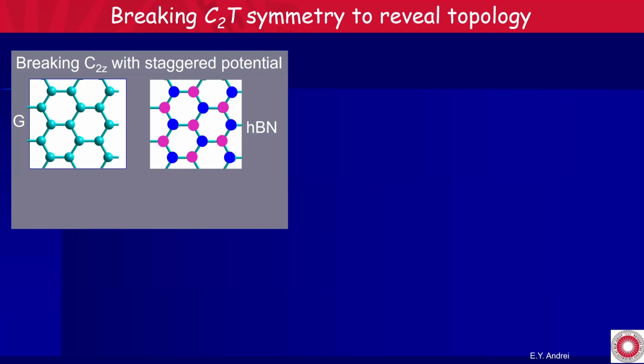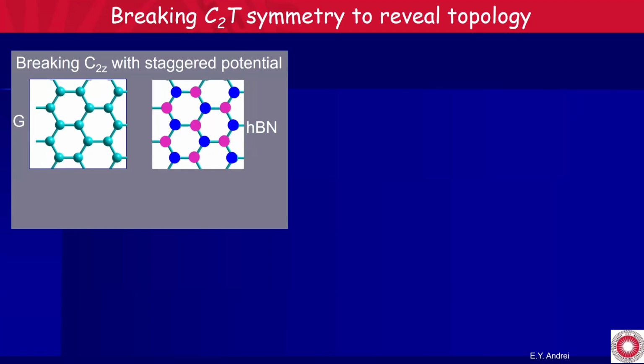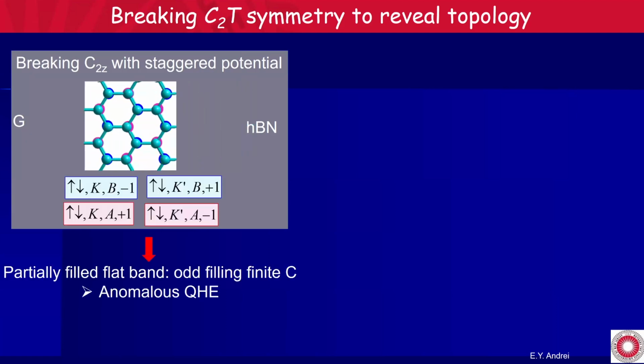So now if I superpose the two and I naively just do this, I see that, of course, you break the symmetry, and the carbon that sits on top of boron is more stable, has a lower energy than carbon that sits on nitrogen. So now we have split the degenerate level into these pink levels where carbon sits on boron and the blue level where carbon sits on nitrogen.